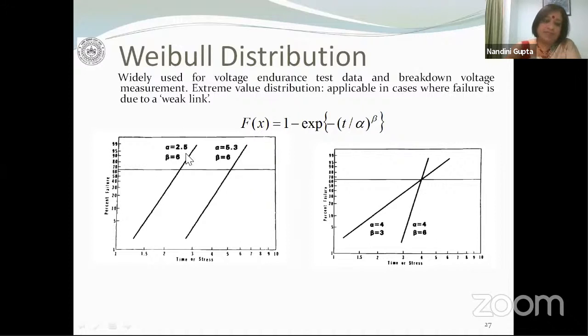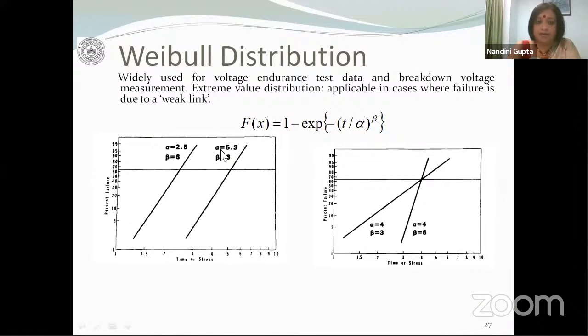In one case, alpha is 2.5. In the other case, alpha is equal to 5.3. If you look at the x-axis, the random variable is either time to failure or the breakdown stress, and therefore it is completely obvious that we will choose the material with the higher value of alpha equal to 5.3 because this material is going to be able to withstand greater stresses.